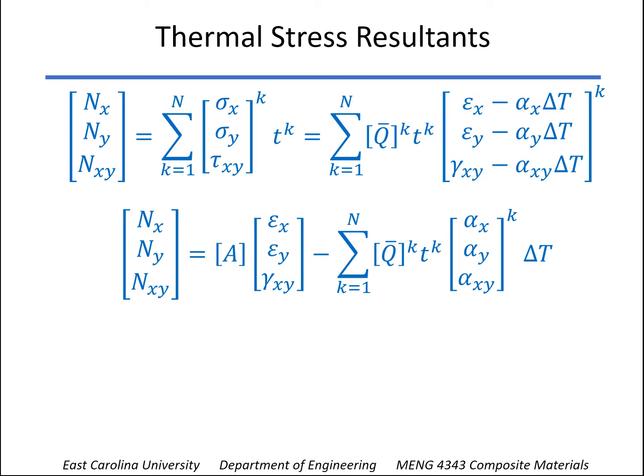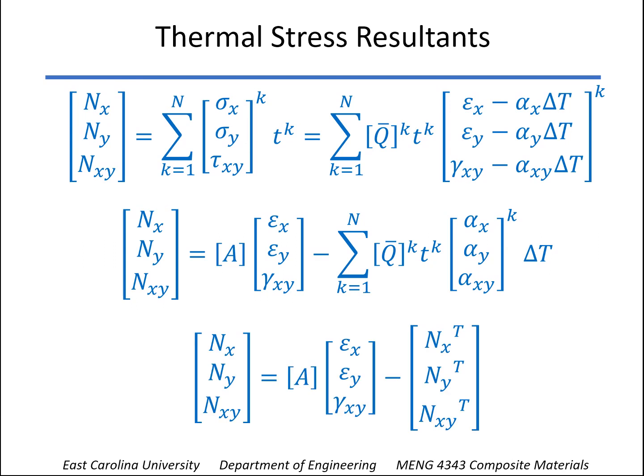So you can see what I've got is the A matrix times the total strains minus that summation, which includes for each layer the Q bar, the thickness, and the alpha values of that layer, all times delta thickness. Excuse me, delta temperature, sorry. And so what's on the right side there after the minus sign, those are the thermal stress resultants: Nxt, Nyt, Nxyt.